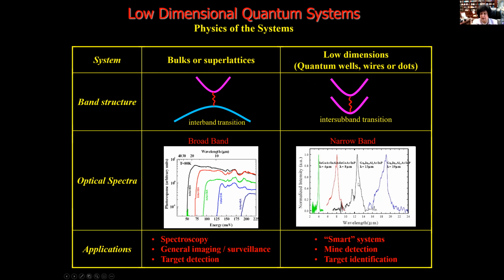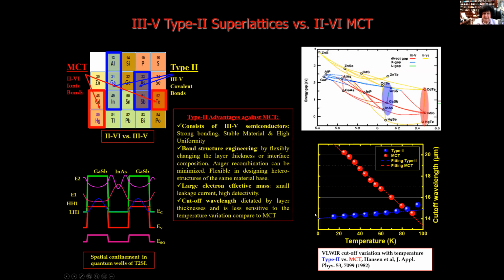But if you look at the QWIPs and all of that, they are narrowband. So that is the reason, again, we came to the type-II superlattices, and comparing with mercury cadmium telluride, here you have the band energy gap as a function of the lattice parameter. Here is the cadmium telluride, mercury telluride, that, as you can see, goes from the large energy gap to the very low energy gap, and they are perfectly lattice matched to each other.